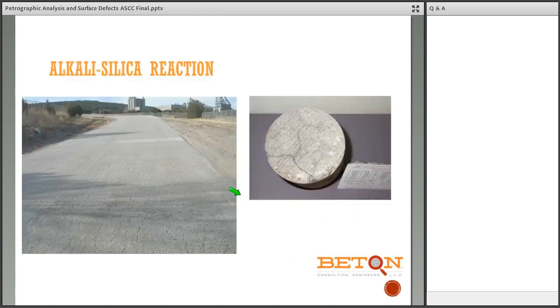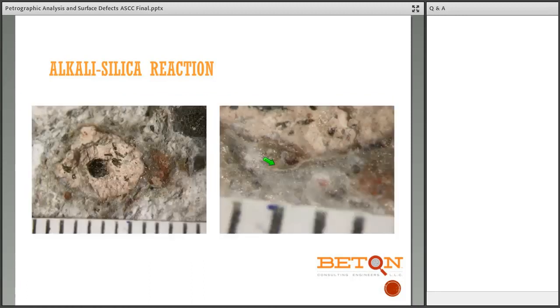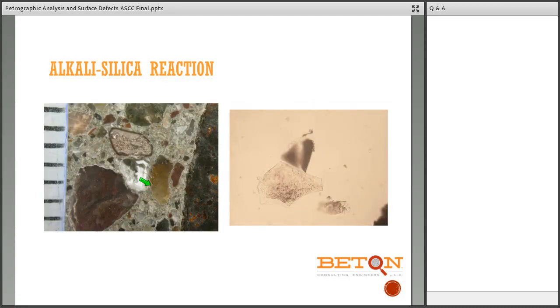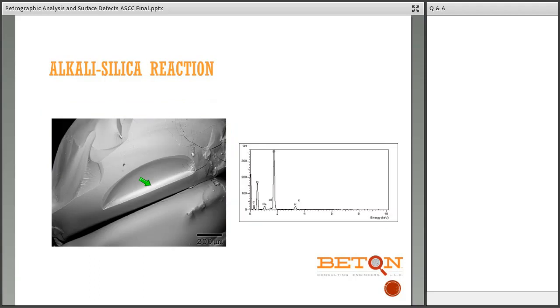Alkali-silica reaction. This is from a pavement in New Mexico, and if you look closely, you can see all the map cracking in this. Core was extracted, and there are several methods we can use to positively identify alkali-silica reaction. One would be a polished hand specimen, in which case you see aggregates with rims and gel. Then you can quarry out the gel and do a refractive index check on it, just to make sure that it's alkali-silica reaction gel. And then use a scanning electron microscope to get the chemistry of the gel, which can tell you a lot. Usually it's rich in silica, and it will have either sodium or potassium. This one has both, which would be indicative of an expansive gel.